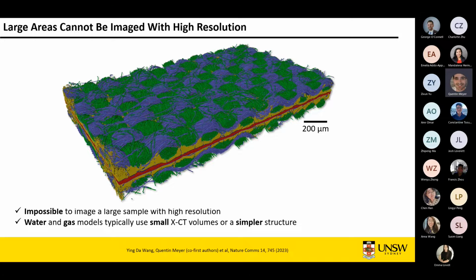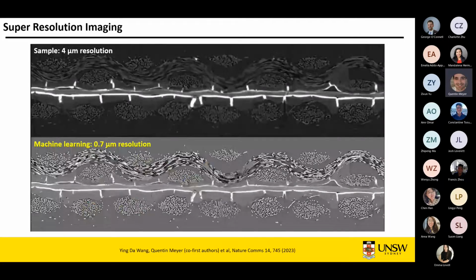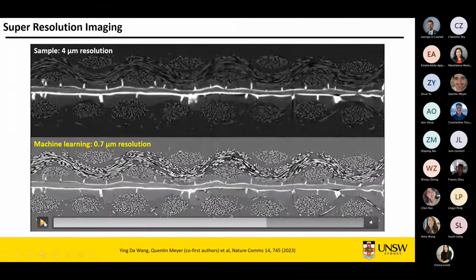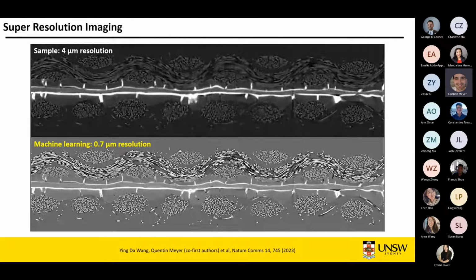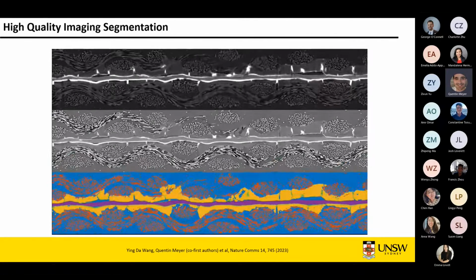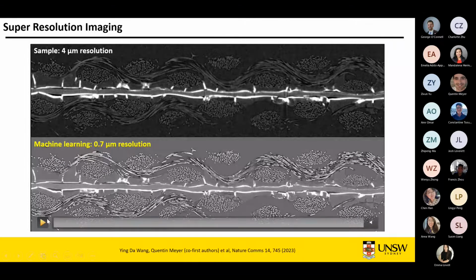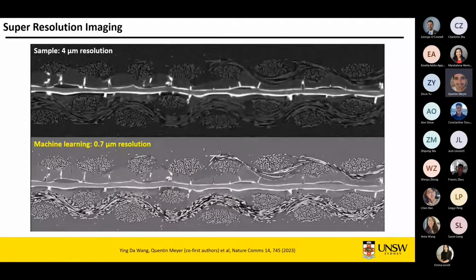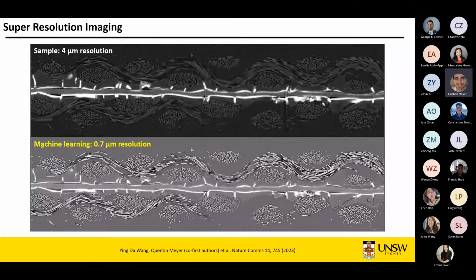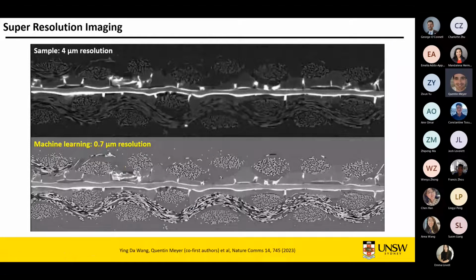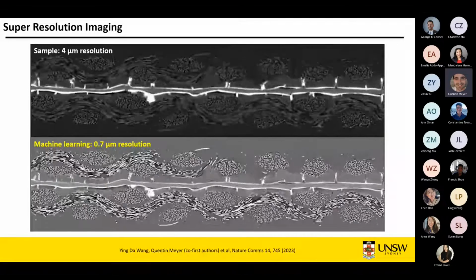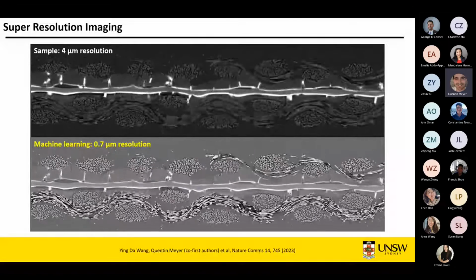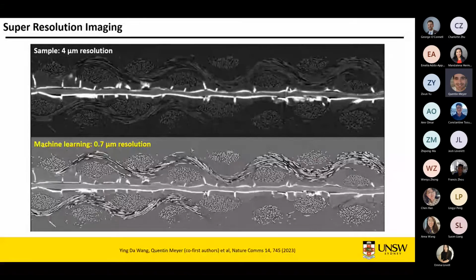So what we've done instead with our collaborators from Green Earth Sciences Building in petroleum engineering in the School of Mineral and Energy Resources, I think I'm saying the name correctly, is basically developed a new approach called super resolution imaging. On the top side, we've got basically a CT image of a fuel cell, and what looks like it's moving, oh, go back, that happens all the time, is we're actually moving through the thickness of the fuel cell. And what happens basically is you've got your carbon fibers here, microporous layer in bright white, you've got a catalyst, you've got your membrane here, and the other side is symmetrical. The problem you've got, the 4 micron resolution, is your carbon fibers are about 5 microns. So with 4 micron resolution, you actually can't really see a single fiber. You've got more like big lumps of clumped fibers together. You can't see much of that.